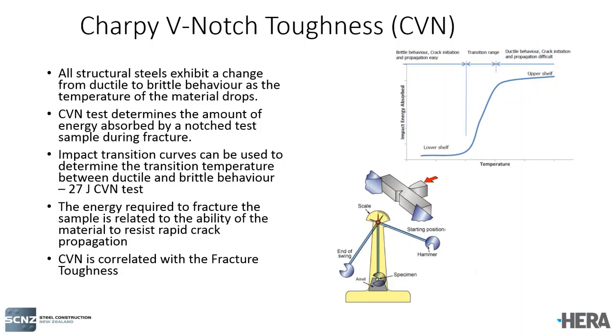All structural steels exhibit a change from ductile to brittle behavior as the temperature of the material drops. The Charpy V-notch impact test determines the amount of energy absorbed by a notched test sample during fracture. This is a test specimen here. They put a V-notch in it to introduce a stress concentrator into the sample. The test consists of swinging a pendulum, and they measure the amount of energy that's absorbed in fracturing the sample, and you can develop impact transition curves for a steel by taking samples and testing them at different temperatures.